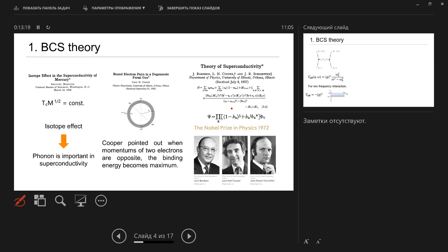But now we know that the superconducting phase transition is a second order phase transition with U(1) gauge symmetry breaking. This means that the system will choose a certain global phase, and the particle density is the conjugate variable of the phase, exactly like momentum and space, or time and energy. When you have an exact phase, it makes the uncertainty of the particle density infinite. That is, one can have an arbitrary number of Cooper pairs in this kind of system. And back at that time, the wave function was really a great discovery.